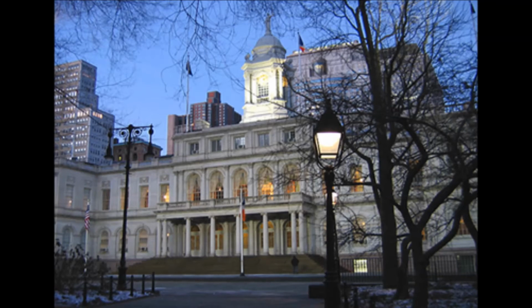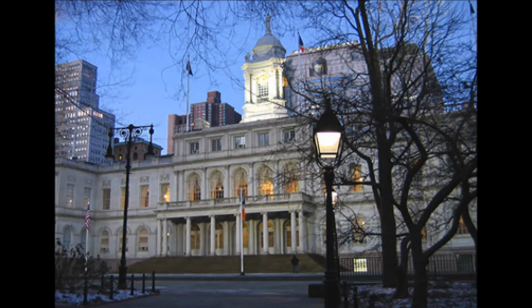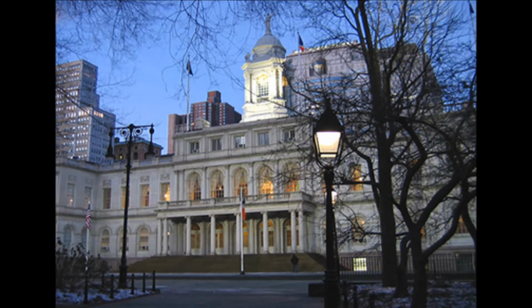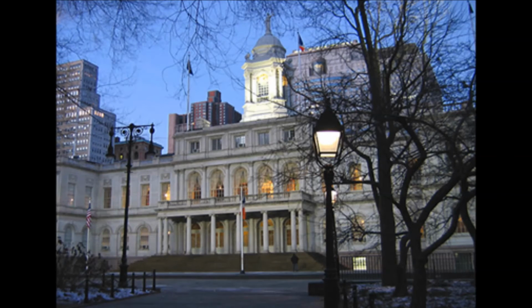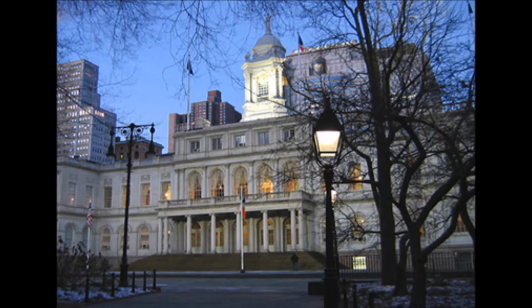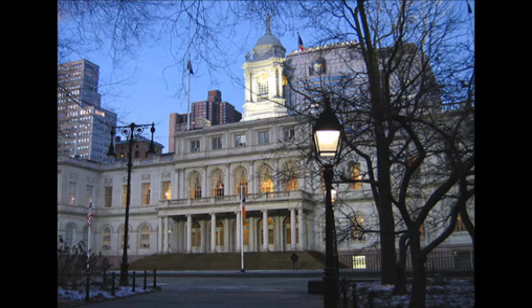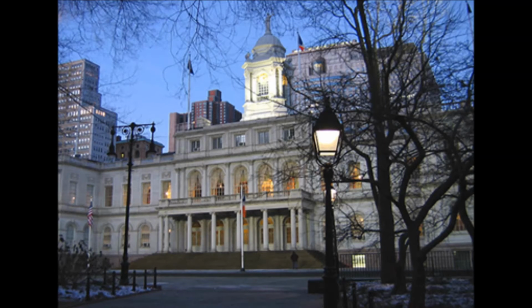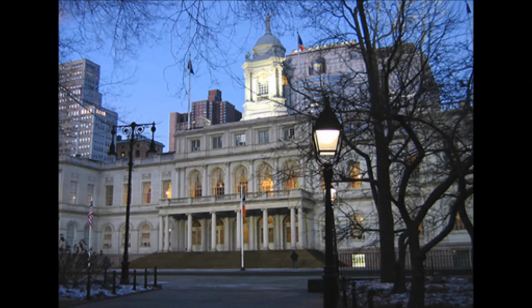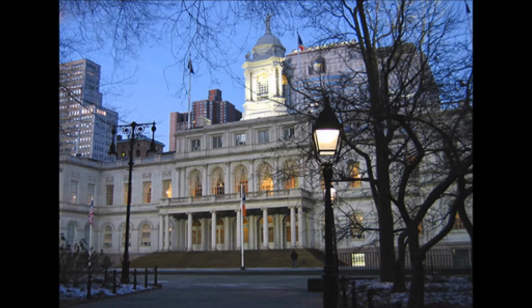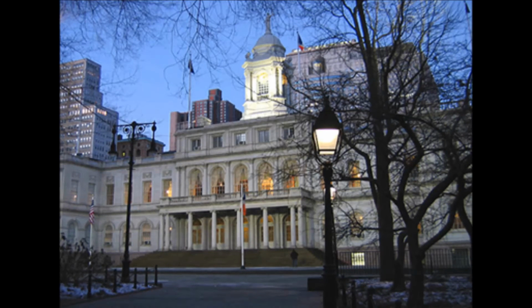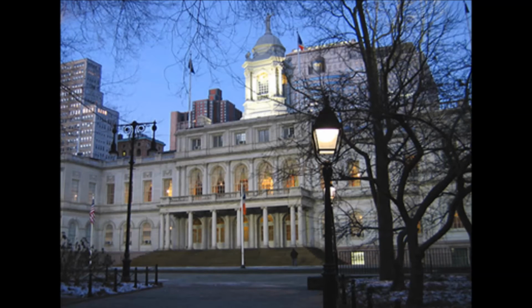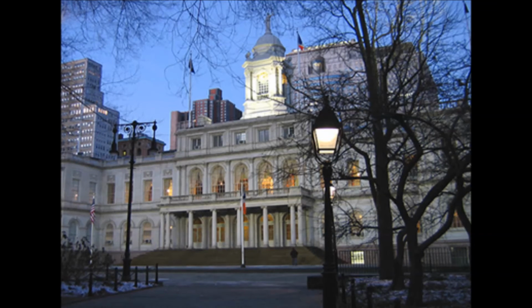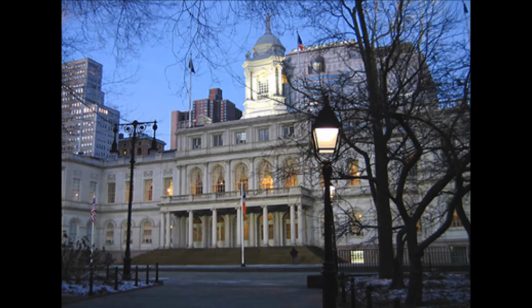I don't know if you can make it out on this projector very well, but you can kind of see the edge here. This is original mortar, and this is original mortar, and there's a little bit of original mortar in here. The slightly wider material in there is compatible injected fill. This is a core that was taken out of a wall that was injected. And you can see how well it fills very small nooks and crannies. We'll have some other demonstrations of that too.